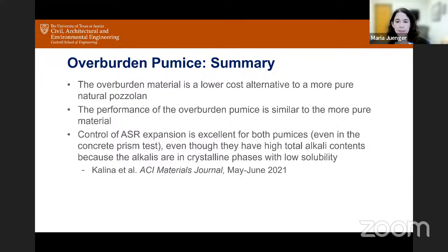We have more data on this. I'm just showing examples here, but from all of the testing we've done, this overburdened pumice material is a lower cost alternative to the more pure material, but the performance is quite similar in spite of the small difference in amorphous content. The control of ASR expansion is excellent for both. There's some concern in the community about the alkalis present in these natural Pozzolans because their alkali contents are pretty high, but we've shown that it doesn't affect their ability to control ASR because these alkalis are not soluble. So they're really quite good materials when you're looking for replacement of a fly ash.